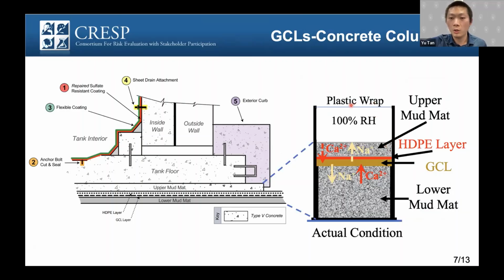We set up the column test in our lab to simulate the lining system in the field. First, we put the lower mud mat at the bottom and put GCL on top of the lower mud mat, and a layer of HDPE on top of the GCL, and we pour concrete on top of the HDPE geomembrane to simulate the lining system in the field.